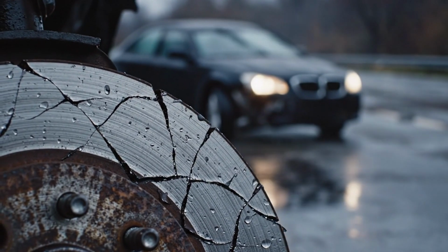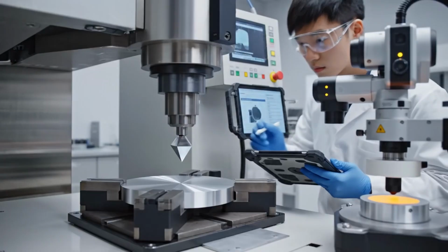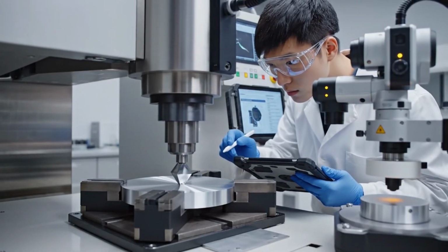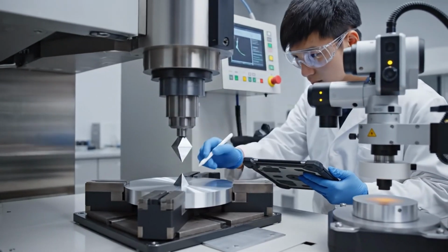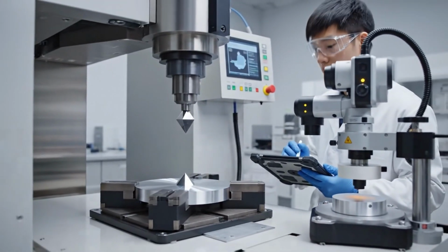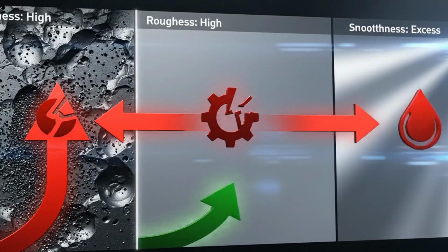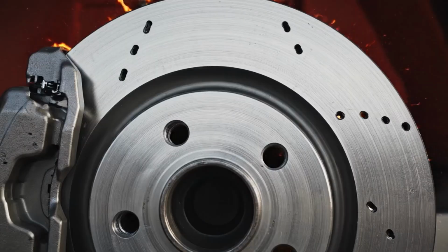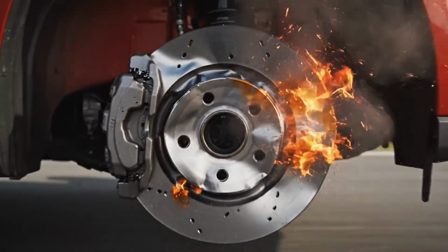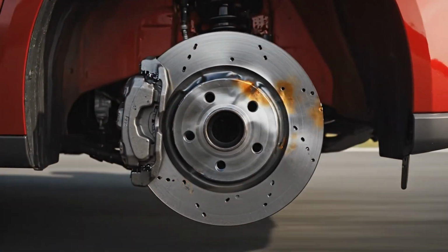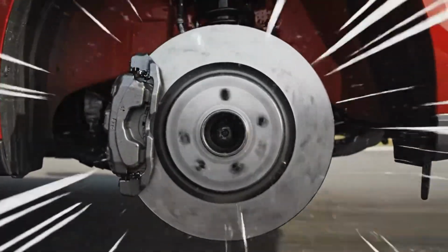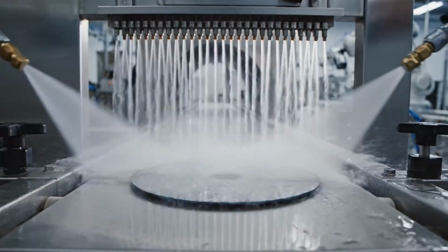At this stage, the material's hardness, thermal response, and surface finish quality can also be checked. Each parameter has a direct impact on final performance. An excessively rough surface could accelerate wear. Incorrect hardness would alter the interaction between the disc and the pad. Poor thermal stability would increase the likelihood of warping. Everything is connected. Once the disc passes inspection, it enters the cleaning and protection phase for shipment.